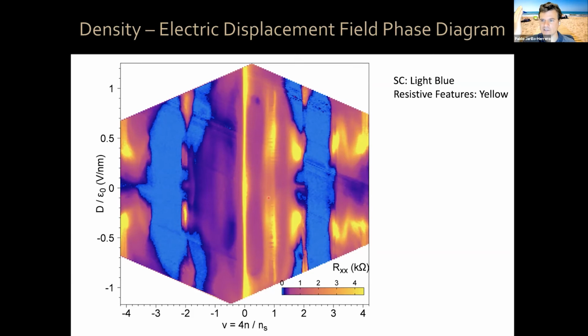As you can see, this diagram has certain symmetry. First of all, top to bottom. So you can see that these branches, these features, there's symmetry top to bottom. That means that the twist angle between the bottom and the middle and the top and the middle layers are very similar. Otherwise, the displacement field would give you an asymmetry. You also have a certain degree of symmetry between the right and left parts. For example, superconductivity occurs mostly between 2 and 3 holes per moiré unit cell and between 2 and 3 electrons per moiré unit cell, but you have these branches also, which are largely left-right symmetric.